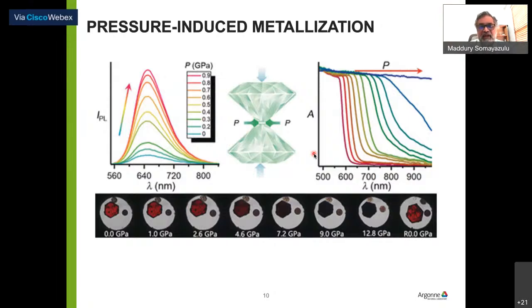But then you also have this situation. I just picked this up from some available review, where you can change the state of the bands in a material. So for example, you can increase the overlap between the conduction band and the valence band in materials, and you come into the very often known phenomenon called pressure-induced metallization, which is pictorially shown here, where something which is optically transparent becomes optically opaque or metallic. And at the same time, releasing the pressure brings it back into its insulating or non-metallic state.